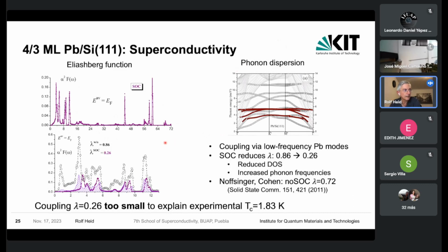Now, a little bit of a surprise came when we did this calculation. When one does this calculation without spin-orbit interaction, one finds a reasonably large coupling constant of 0.86, but this is significantly reduced when we switch on spin-orbit interaction. Partly the reason is the reduction of the density of states, as I mentioned before, and another is that the phonon frequencies of the lead vibrations at the surface become harder when we switch on spin-orbit interaction.